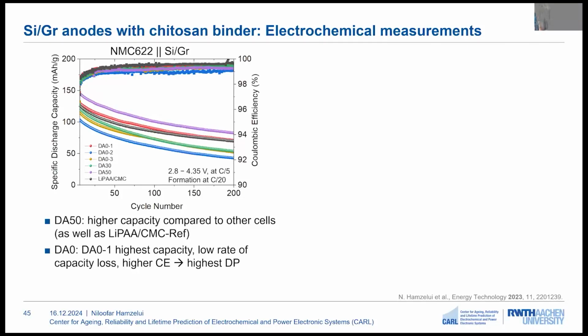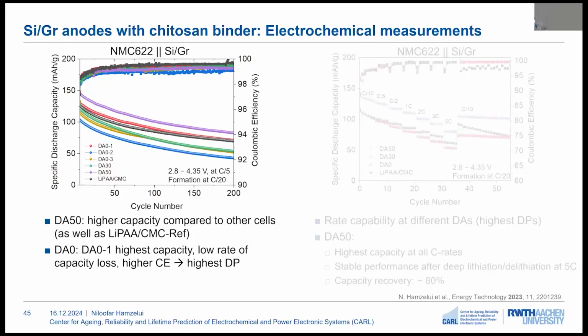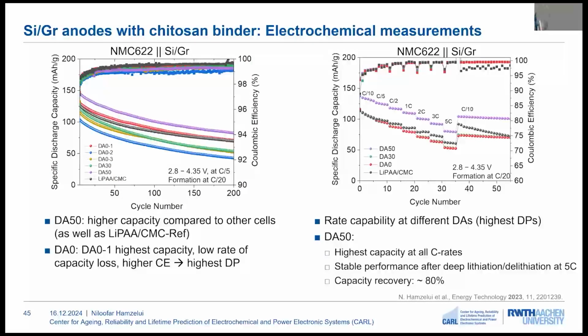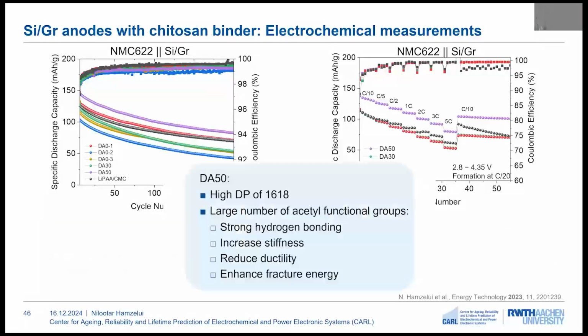In case of DA0 binders, again, we can see that DA0-1 has the highest capacity and a higher Coulombic efficiency, and this is the binder which had the highest degree of polymerization, similar to the degree of polymerization of DA50. Again, the rate capability of the cells was investigated in the full cell. And here we can also see that at all C rates, we are having a higher capacity using chitosan with DA50. And we are also seeing a stable performance in these cells and a capacity recovery higher than 80% after deep lithiation and delithiation at 5C.